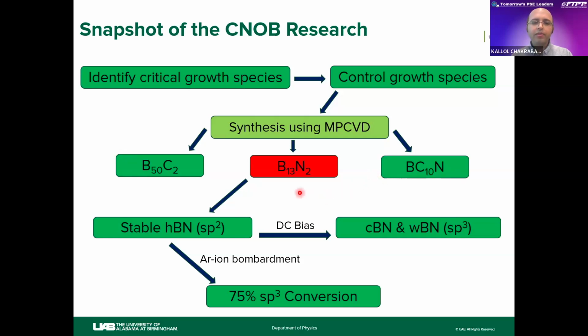Although we are not able to synthesize the superhard boron-rich boron nitride, we got some insights from this project, and we are able to synthesize stable hexagonal boron nitride. Then we introduced DC biasing in our microwave plasma CVD chamber, and we can get cubic boron nitride and other boron nitride from this chamber. Next, we introduced argon ions in our gas, and we can convert 75% boron nitride to cubic boron nitride.